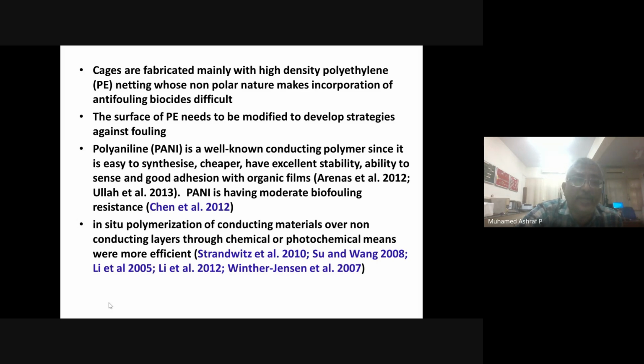So to avoid that, first we have to modify the surface of the polyethylene because it is non-polar. So we have to make it polar, that means add some conducting molecules like polyaniline. So we tried to synthesize polyaniline over aquaculture cage nets, or over the polyethylene, by immersing, but it is not at all working out.